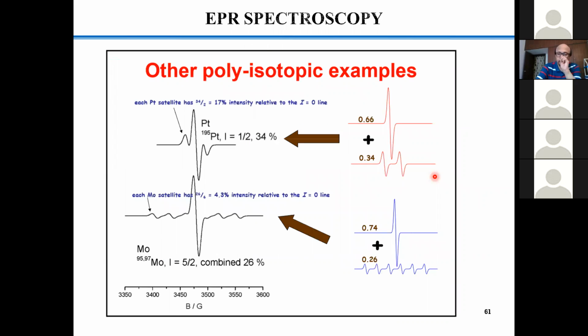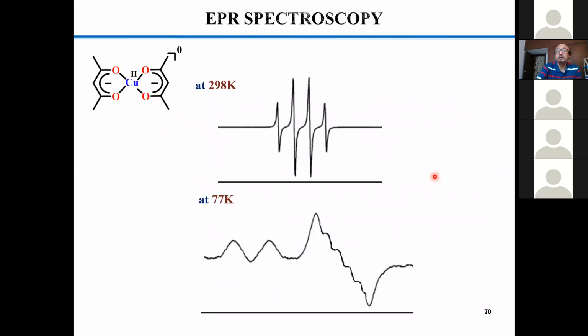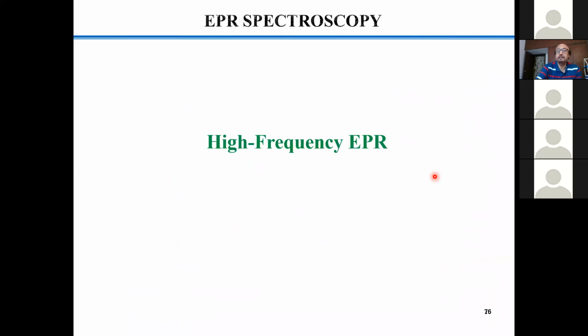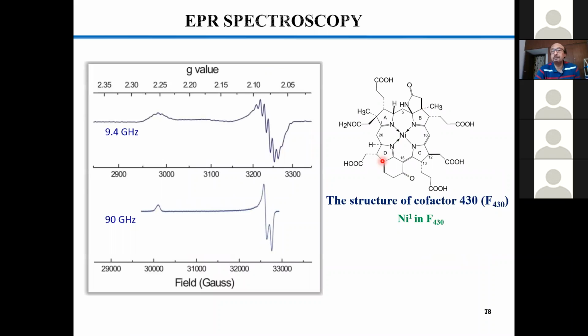As I said, if you get the crystal structure, then you can prove whether any metal nickel solvent interaction is there at all or not. Okay. Now, if you do not have the X-ray structure, then through EPR you can guess something, and you could get the sense that something is here along the G-axis. If you do not consider something over here, as far as the ligand and metal ligand interaction, then it's a perfectly square planar type of situation. And perfectly square planar type of situation is a Z-out situation, right? Tetragonally elongated situation. So you have a somewhat C4 axis over there. Okay, and then you can expect to have this kind of EPR,